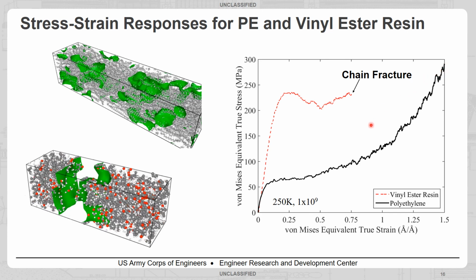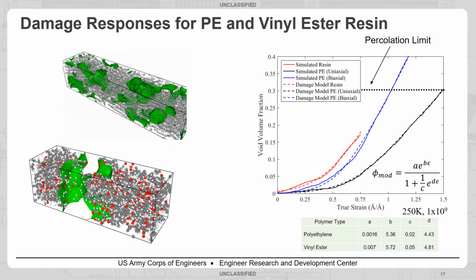But we'll here show it up to 1.5. So very different failure mechanisms, as we would expect. Very different stress strain curves, as we would expect. So we do a good job at capturing that phenomenon. Then we can look at the damage. So we have our simulated damage, and then we can also fit a model to it.